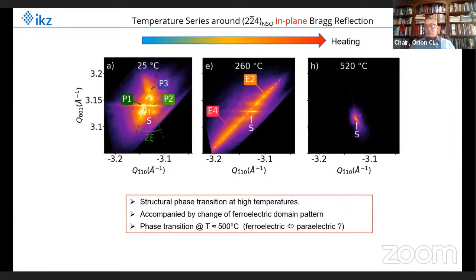At room temperature, you see a typical fingerprint of the herringbone pattern. You see the peaks P1, P2, which arise from the A1, A2 phase, and you see the peak P3, which arises from the monoclinic MC phase. When you heat up the samples to high temperature, we see a change in the diffraction pattern, indicating that we have structural phase transitions at these high temperatures. When you further heat up the sample, you end up with the paraelectric phase at about 500 degrees centigrade.